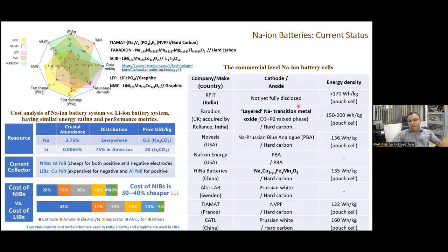And as one can see here, even though layered sodium transition metal oxides would have been the first choice for the cathode material because they can have the highest possible sodium storage capacity, we can see among the commercial prototypes, not all have the layered transition metal oxides. Probably only these two have right now. And the others have prussian blue or sodium vanadium phosphate, which are the other classes of cathode materials. The reason is the challenge associated with the layered transition metal oxide. But if we can address these challenges, then layered sodium transition metal oxide cathode materials can be used in commercial level sodium ion cells, and that can elevate the energy density of the sodium ion batteries to a significant extent. So that is one of the major objectives of sodium ion research worldwide.